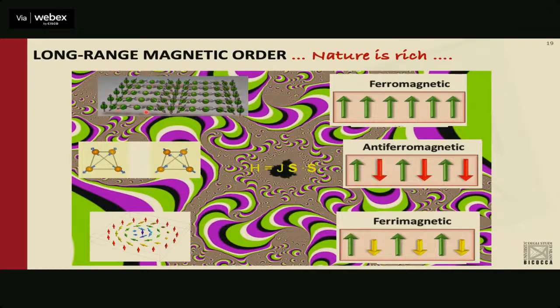But what is fascinating is that it can also get non-collinear, kind of spiral. So from site to site, the direction of the magnetic moment changes. And they can also go non-coplanar. So they can, for example, point along the center of a tetrahedron, or you can have even more complex, so-called topologically non-trivial spin configurations like a skyrmion and anti-skyrmion. And you really find these examples of complex ordering in materials. And as you can imagine, understanding why they adopt this complex ordering is an intriguing question.